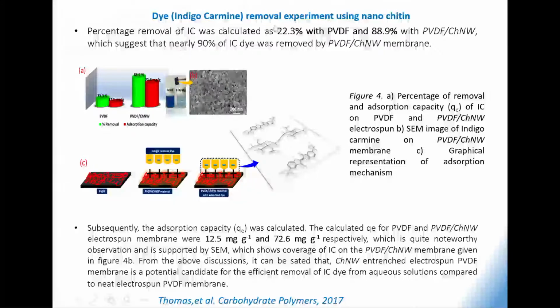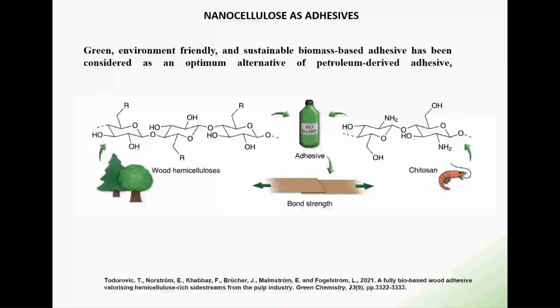You know what we did? We decided to make hybrid structures of PVDF and nanochitin. Because we were making nanochitin in my laboratory, we decided to make a hybrid configuration by electrospinning. So we introduced nanochitin into PVDF, we went for electrospinning, and you see, if you use only PVDF, the removal efficiency of indigo carmine was 22.3%. But if you combine with nanochitin, look at the removal efficiency, 88.9%. And we have a patent with my Slovenian counterpart, and we also published a series of papers by combining nanochitin and PVDF for the removal of indigo carmine dye.